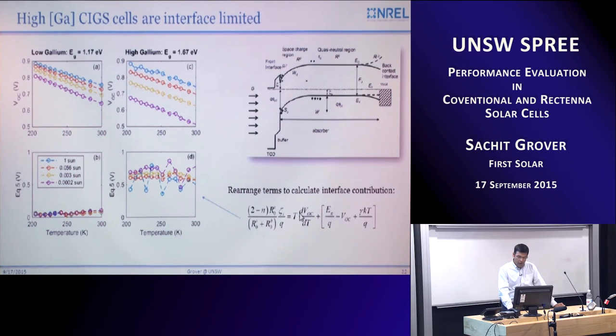I take experimental values for VOC and temperature derivative of VOC and plot that right-hand side, which basically reflects the interface recombination. And I do that for the low gallium and high gallium device in the CIGS cells that I mentioned before. Here's the VOC as a function of temperature for different light intensities for both these cells. And if I perform this calculation, what I see is the low gallium device shows a very small number independent of light intensity, and the high gallium device shows a very large number for this equation, basically saying that there's more interface recombination happening in the high gallium device, which we knew, but again, this is another way to look at the same data, another way to confirm that.